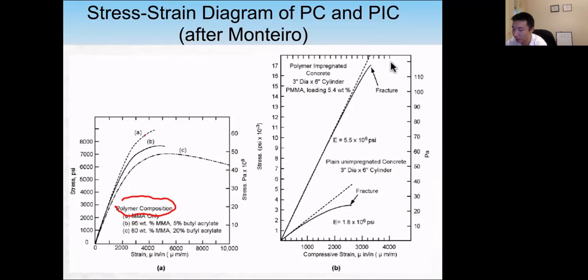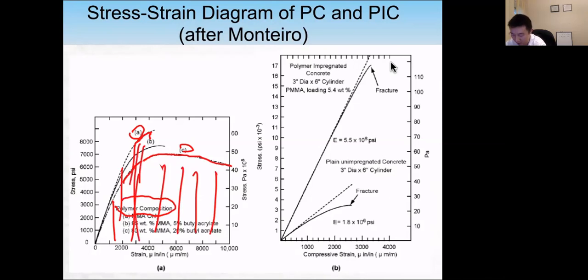For MMA only, the material is very brittle, so after the peak load there is almost sudden failure. But for C, after the peak load, the concrete can still resist a certain amount of load. So the toughness of this concrete is much higher compared to A, MMA only. By modifying the composition and percentage of different polymers, we can change the performance of polymer concrete quite a lot.